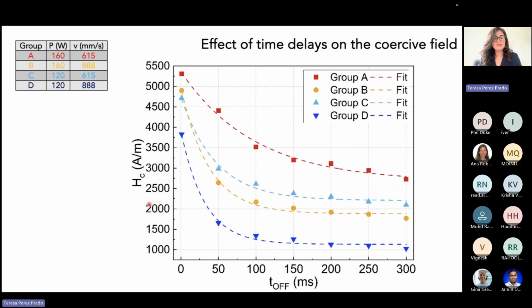Just one final slide to show you what about the magnetic properties. So here I'm plotting the coercive field versus the delay time for all this group of samples. And of course, the coercive field decreases with the delay time because we are increasing the amorphous fraction, but still our target is 10 amperes per meter. We are still in 1000.